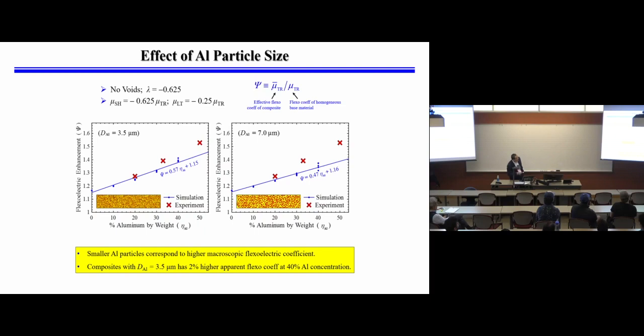Particle size. Just quickly, if you increase the particle size, you actually have less electrical output. So smaller is better in this case. We just randomly chose, without voids, so we're not trying to match the experiment, but just to purely explore the trend: smaller is better if you want more electrical output for the same amount of deformation, the same amount of bending.